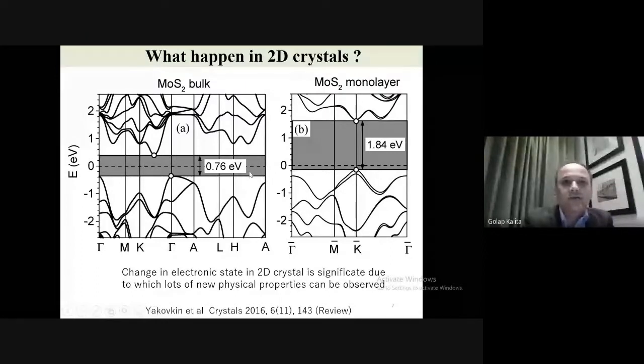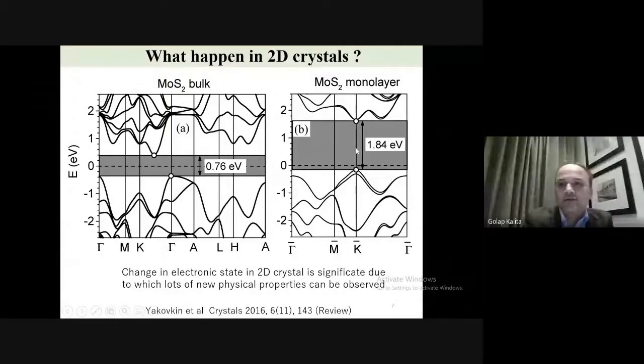Now, if you just take one atomic layer of MoS2, the band structure totally changes. So it becomes a direct band gap semiconductor. So the highest position for conduction band and valence band, if you see, it's a direct band gap semiconductor with a band gap of 1.84 electron volt. So when you make 2D materials from bulk materials, the electronic properties as well as the optical or chemical properties vary significantly. And when you have this kind of direct band gap, you can do many things. It's very interesting for optoelectronic properties.